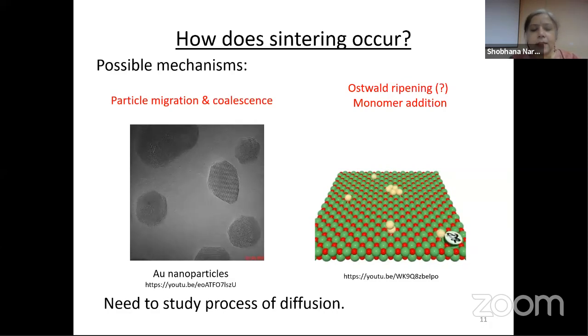I couldn't find a similar video, which was an experimental video for the other process, which is of interest, which is what people refer to as Ostwald ripening, though it's not quite Ostwald ripening. It's a process of monomer addition. So this is a molecular dynamic simulation, which shows that single atoms are diffusing on the surface, and then they're joining larger islands, and slowly the particle is growing.